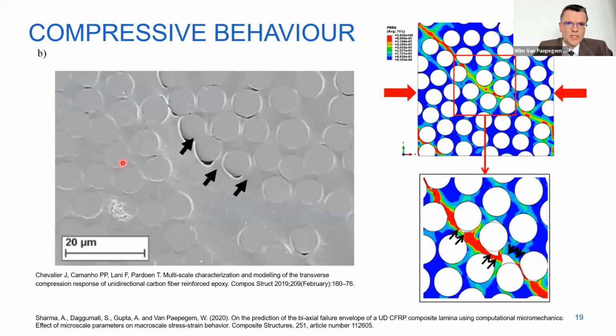It becomes a bit more tricky when you go to compressive behavior. Here you see transverse compression. And there again, we try to validate our simulations by looking at shear bands and shear band angles, and also at details from experimental observations. Here you see a sort of cusp behavior or a sort of opening, and we also see that in the simulations. But we observe here also another problem.